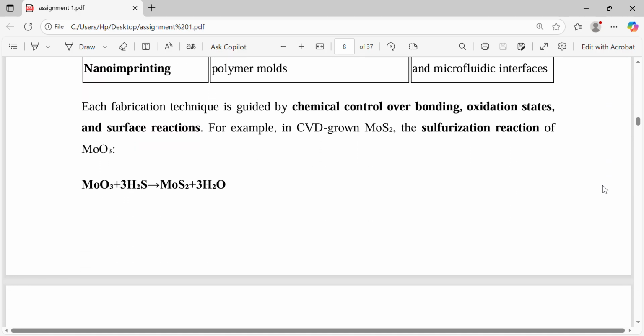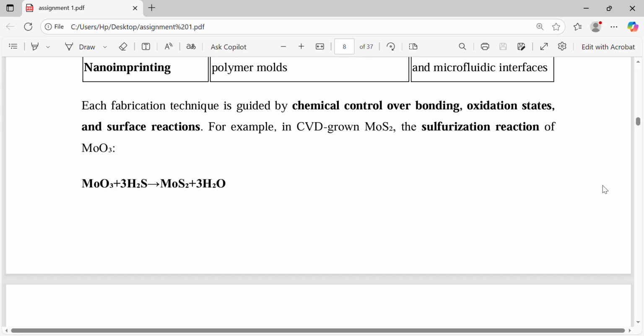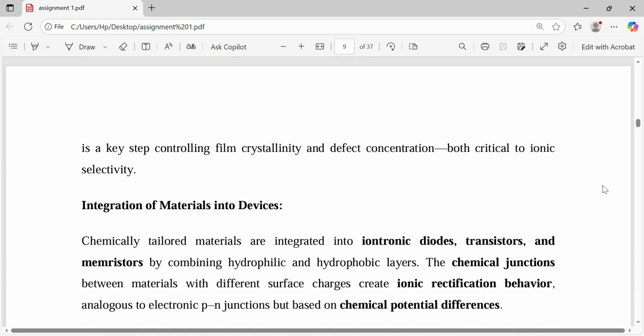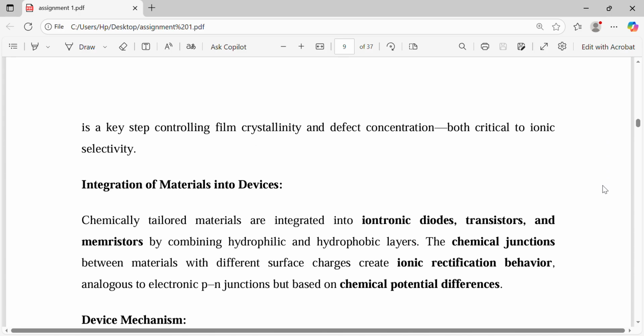Each fabrication technique is guided by chemical control over bonding, oxidation states, and surface reactions. For example, in CVD-grown MoS2, the sulfurization reaction of MoO3 plus 3H2S yields MoS2 plus 3 water molecules. This is a key step controlling film crystallinity and defect concentration, both critical to ionic selectivity.